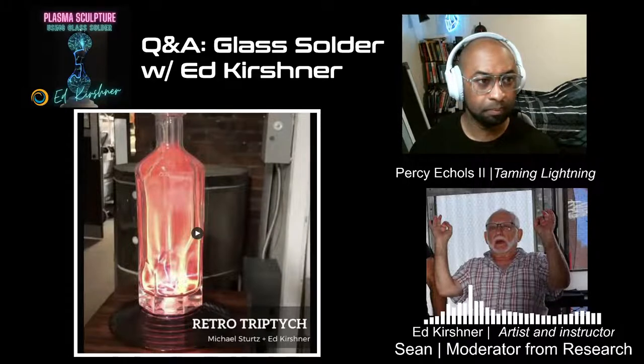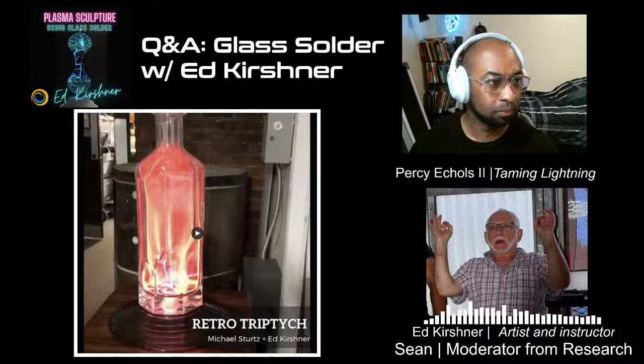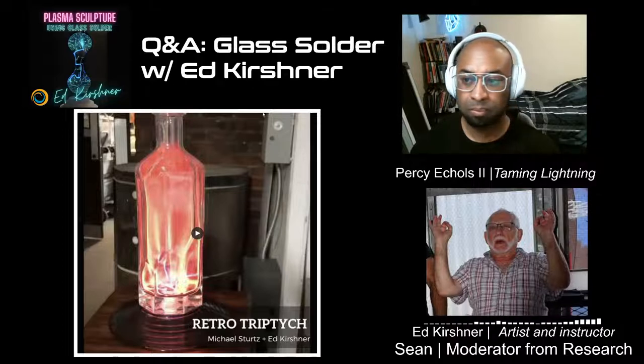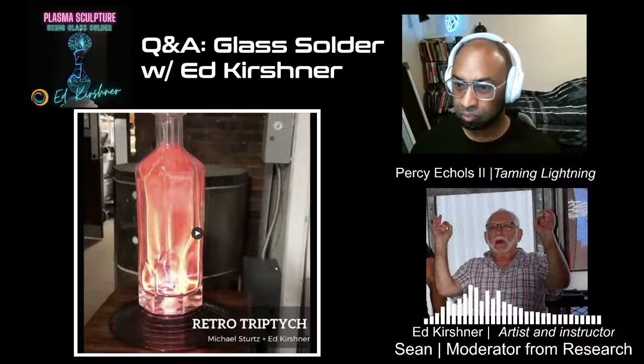In this case, what I did was I countersunk. I drilled down to make the glass thin at the joint part. You can sort of see it a bit. There's a cone. And so at the point the electrode touches up, there's a very thin connection there. And after many tries, I got the solder to hold.